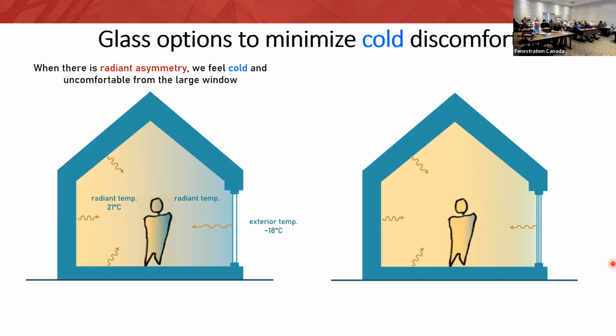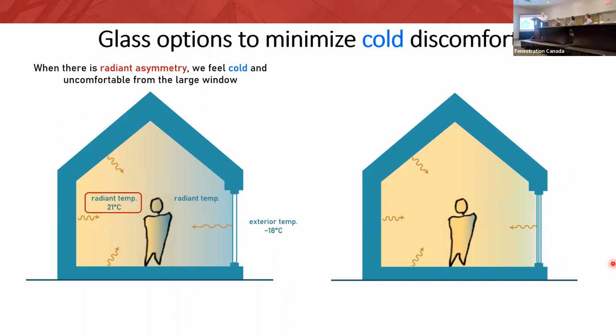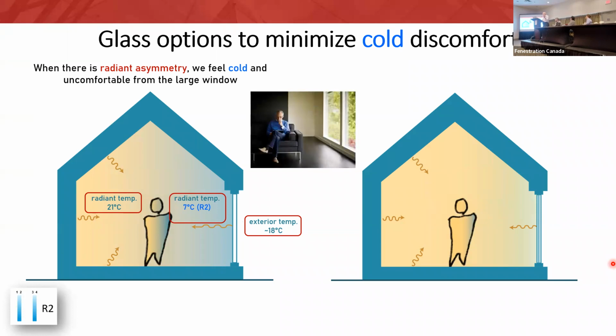So for some reason, I added a slide to revisit radiant asymmetry here. So I'll just go through it. Under NFRC conditions, we have minus 18 outdoors, 21 indoors. And if we had dual pane clear glass, R2, that indoor surface temperature is 7 degrees Celsius. Not very comfortable in terms of radiant asymmetry. And that's why George here is sitting so far from the window.